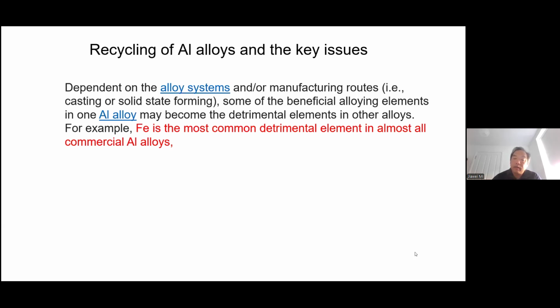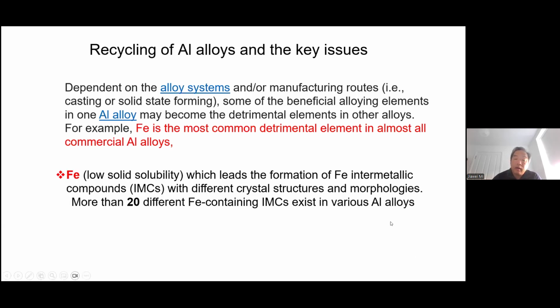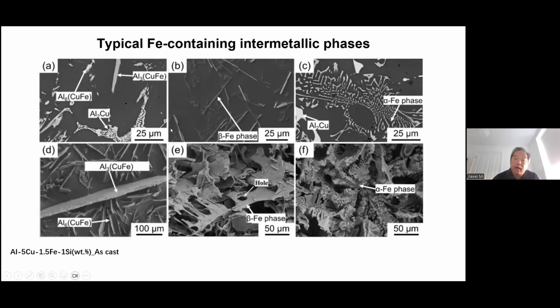And among those, iron is probably the most common and most detrimental element in almost all commercial aluminum alloys, unless some are very special ones. Iron has very low solubility in the solid state of the aluminum alloy, so it forms many different types of iron-containing intermetallic phases. In this example, most of the iron intermetallic phases have very complex morphologies or shapes. Some of them are like a plain plate, like a knife cut into the matrix. That will definitely be a stress concentration region, which will damage your mechanical properties.